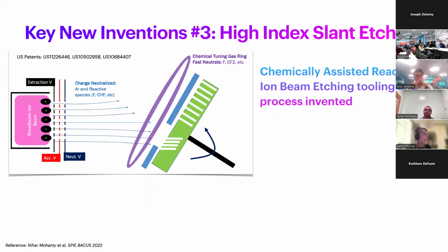Now, the third key invention is anisotropic gratings and enabling high index slant etch. Anisotropic gratings have been well known for their ability to enable asymmetric diffraction efficiencies, which play a crucial role in achieving high performance waveguides. Ion beam etch tools are the key to achieving asymmetric gratings at volume. A typical ion beam etch system comprises a plasma generating chamber from which ions are extracted, accelerated, and neutralized before hitting the substrate at the desired angle to create the desired slant.